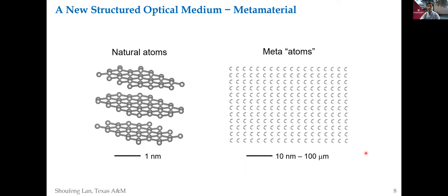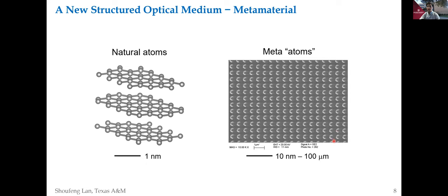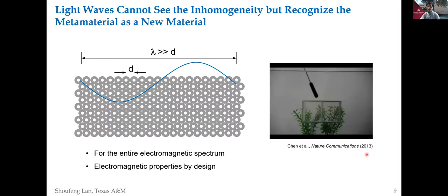The good thing about this length scale is that it's fabricable in a modern semiconductor fabrication foundry. For example, we fabricate a metamaterial that has a pitch of around 1 micrometer. The key to the metamaterial is that you have a structure that is smaller than the wavelength of interest. The reason is that material properties are materials' responses to electromagnetic waves that have some specific wavelengths. So when you change structures that are smaller than the wavelengths of interest, the electromagnetic wave cannot see the change, but rather recognizes the metamaterial as a new material.